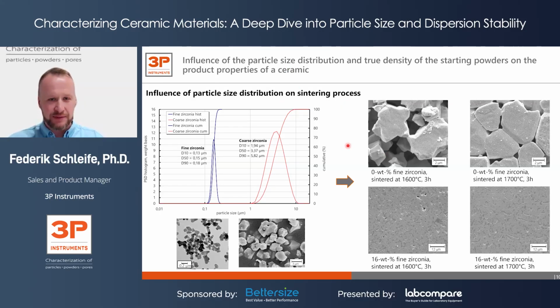After those green bodies had been sintered, you can realize that when there's no fine zirconia added, you only have the 3 micron coarse zirconia powder, and you sinter the green body at 1600 degrees Celsius for 3 hours, you would realize that you do not get a closed structure. So you still have large pores, so the final density is pretty low, and you cannot expect a good performance of this piece of ceramics. Okay, maybe the temperature was simply too low, so it was sintered at 1700 degrees Celsius for 3 hours. Then you can see that the sintering performance is already better, but still there's a lot of open cell content here. There's a lot of enclosed structure, so therefore still not what you want to get for a good workpiece.